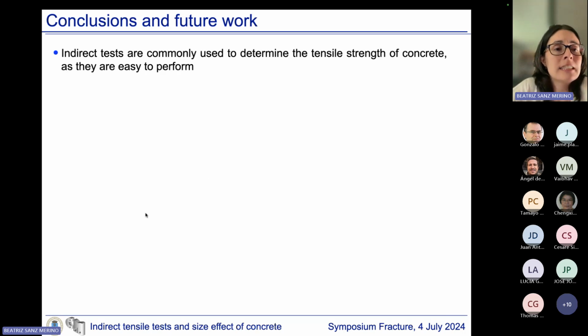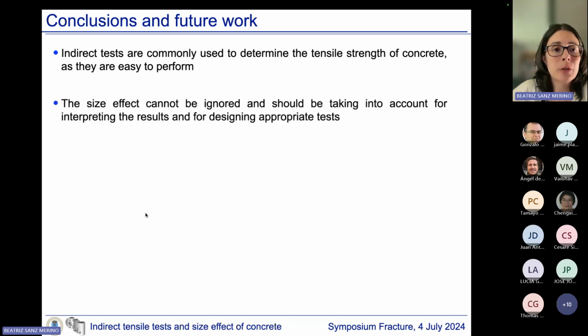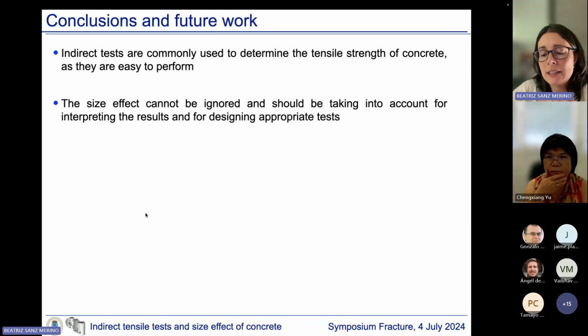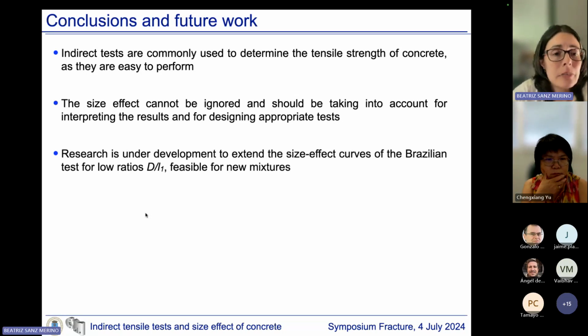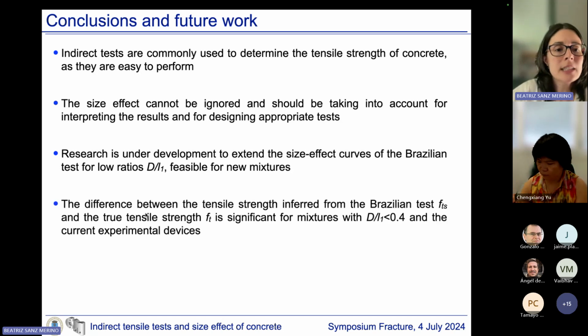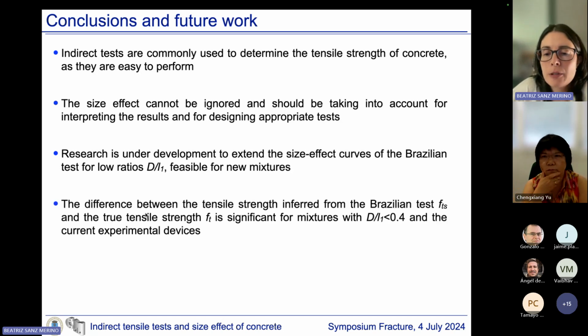Just to conclude, I will say that indirect tests are commonly used to determine the tensile strength of concrete, as they are very easy to perform. The size effect cannot be ignored and should be taken into account, sorry for the misprint, for interpreting the results and for designing appropriate tests. Research is under development to extend the size effect curves of the Brazilian test for low ratios D/l_t feasible for the new mixtures, and the difference between the tensile strength inferred from the Brazilian test FTS and the true tensile strength FT is significant for mixtures with ratio D/l_t below 0.4, and the current experimental